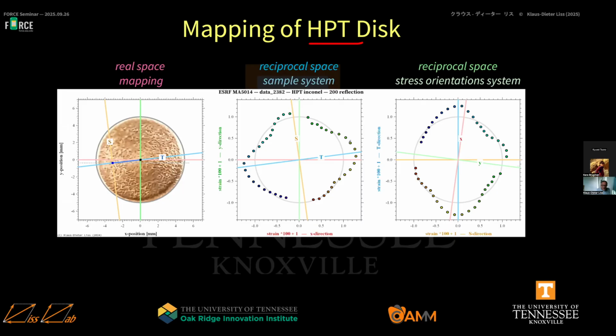In the t direction, I have more positive strain on both in plus and minus, yeah. And also I have some positive strain in the shear direction and less in the direction in between. So this is a typical butterfly pattern, which comes after relaxing shear stress or after relaxing stress, after plastic deformation, because the slip is a little bit more complicated than just applying, because this experiment is not in situ.